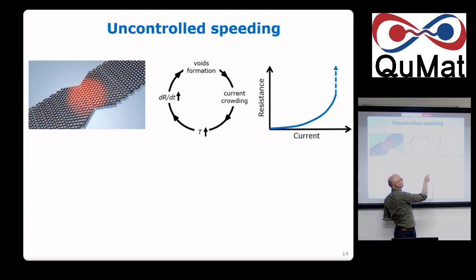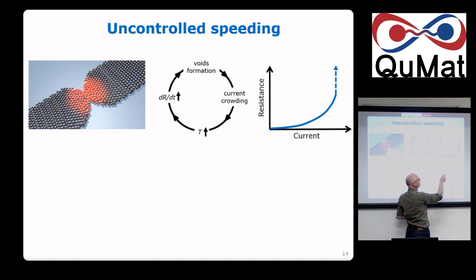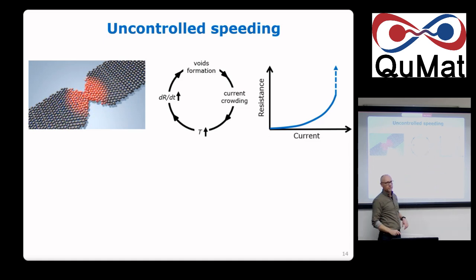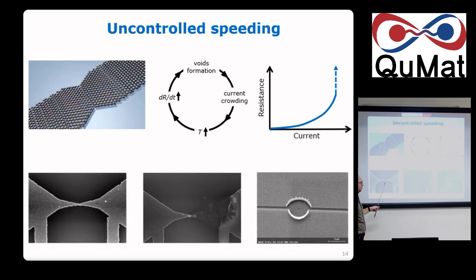So basically, if you measure resistance versus current, you heat up the system. When you start to electromigrate, it explodes. I show you this is the case because we tried. Sample before trying, sample after trying, all blown in the air.